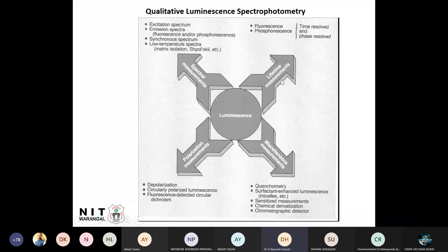Similarly, lifetime measurements: how much time the electron is sitting in the conduction band. I told you fluorescence is 10 to the power minus 8 seconds, and phosphorescence is more than 10 to the power minus 5 seconds, sometimes even hours or days. So how do we determine that lifetime? Using time-resolved photoluminescence spectroscopy, we can estimate the time the electron sits in the higher energy state, the conduction band.